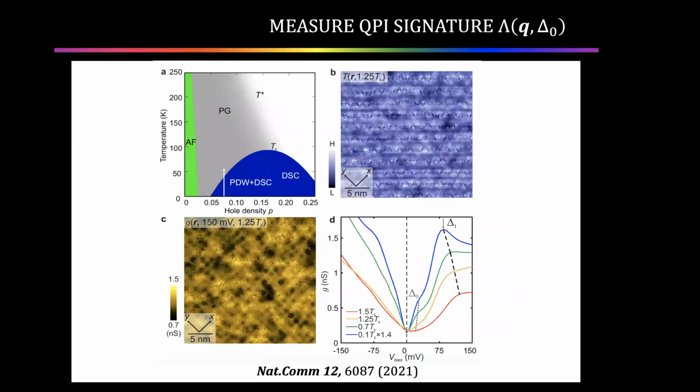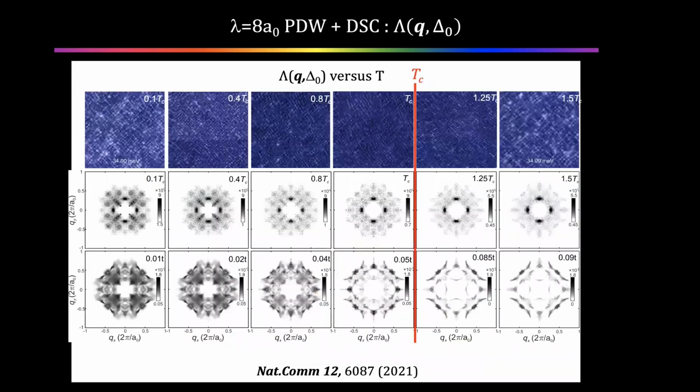Then Chu studied the temperature dependence of the same phenomenon from here to about here, 1.5 times above TC. You see the spectrum going from here, but as we go up in temperature, diminishing away rapidly. So anyone who would like to see these data, I think she'd be happy to show them to you. But here are the Fourier transforms of the integrated scattering interference. And here's the model. Here's the scattering interference detected above TC of the Q equal to zero superconductor.